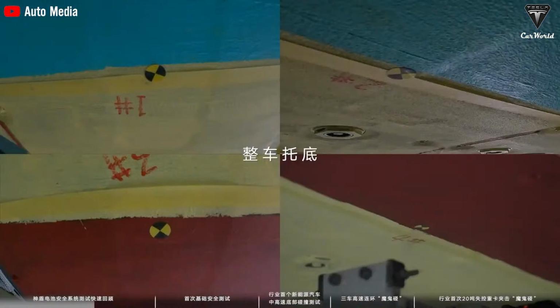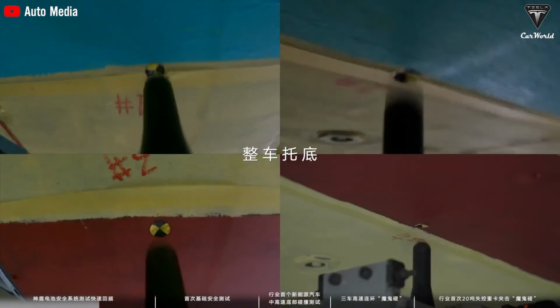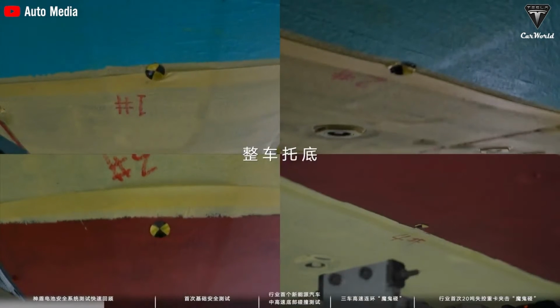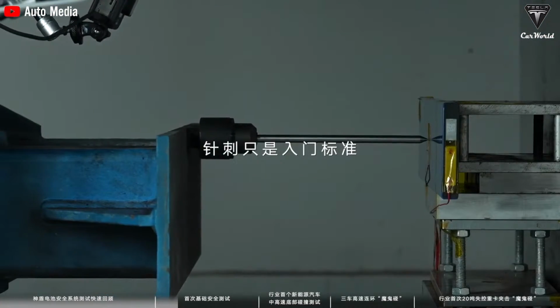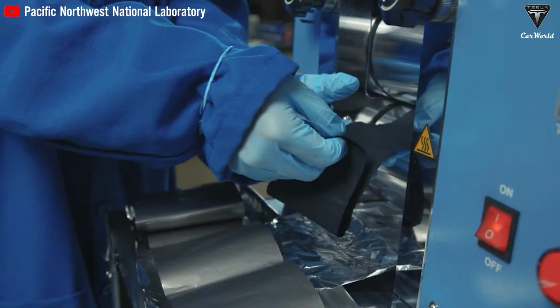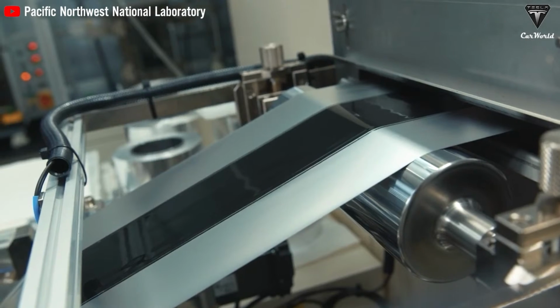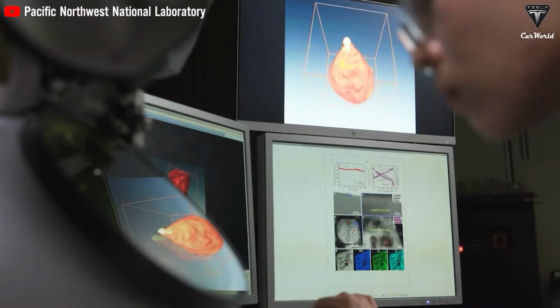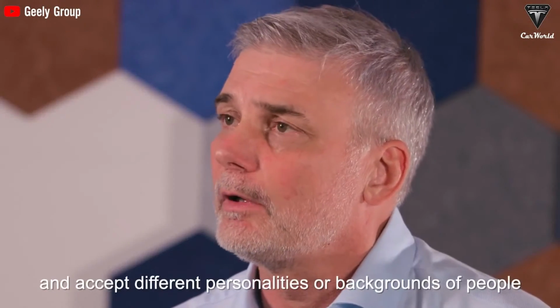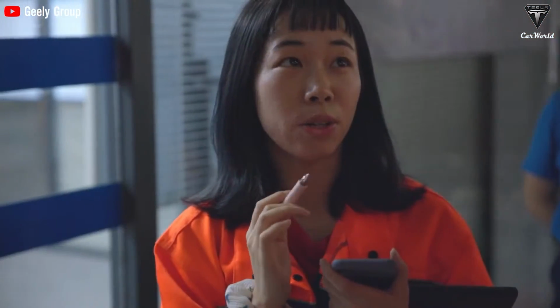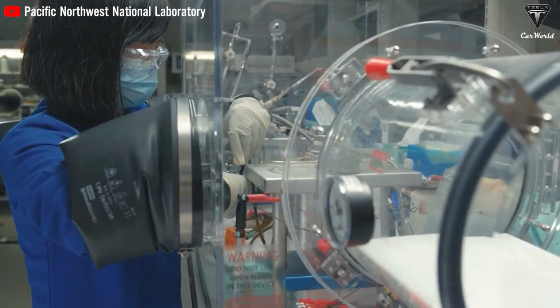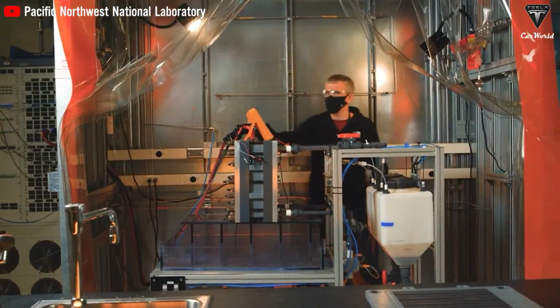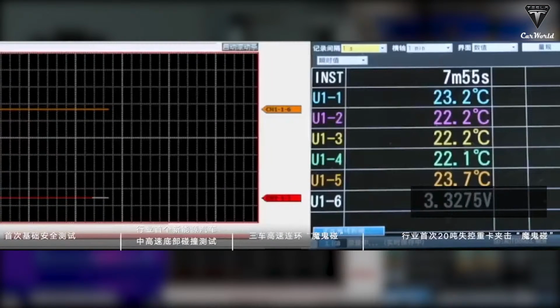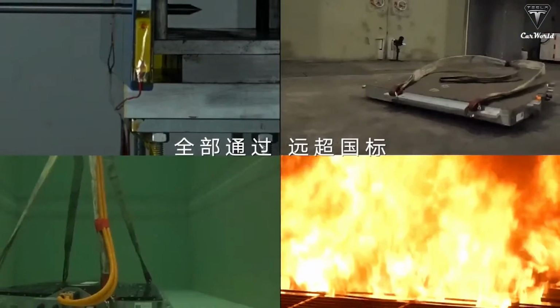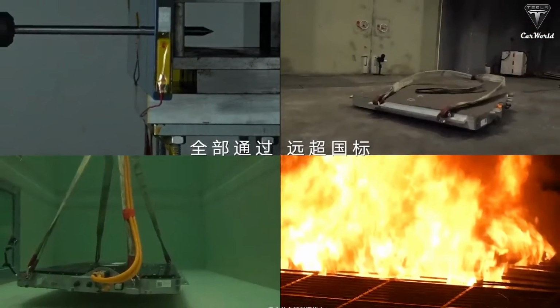During testing, it was punctured simultaneously by 8 steel needles, each 5 millimeters in diameter, and left undisturbed for an hour without any adverse effects. In addition to passing the 8-needle puncture test, Geely subjected the new short blade battery technology to the industry's first 6 extreme limits tests, including immersion in corrosive seawater, extremely cold environments, high-frequency bottom scraping of the battery pack, 26-ton overload rolling, side impact on a single battery pack, and fire roasting.